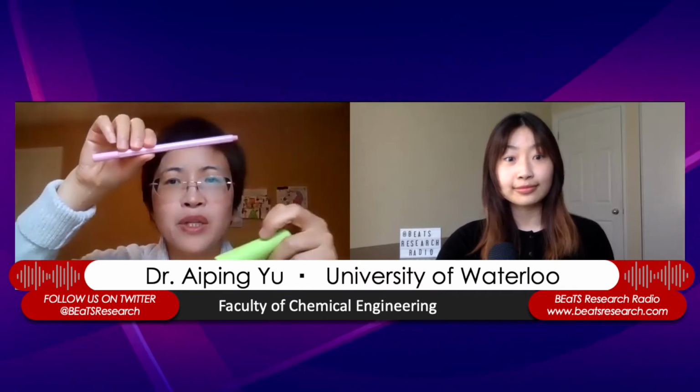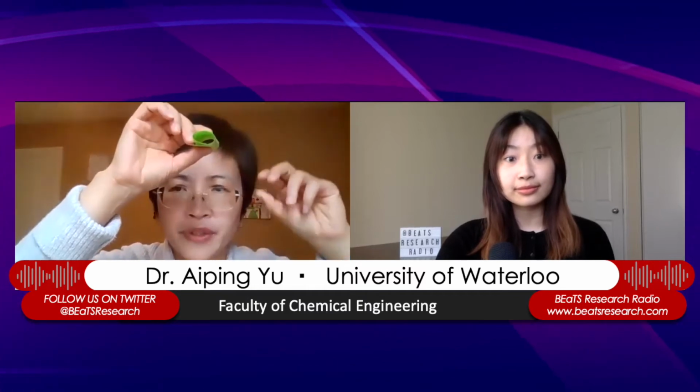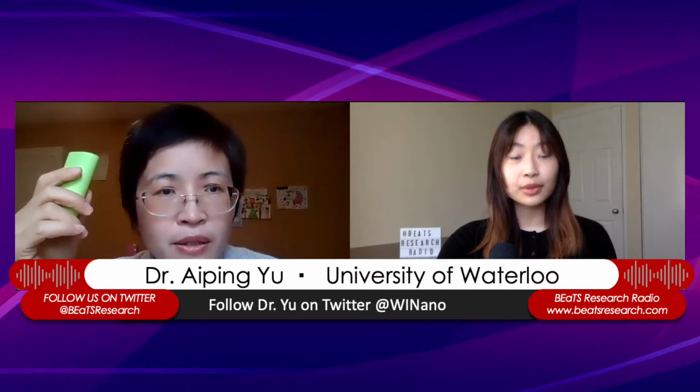Yeah, that's a very good question. As you mentioned, it's related with property. The first property that is different and also amazing is electronic property. For example, single wall carbon nanotube, these materials could be metal. Basically one type, it means this tube, the diameter and the angle, how you roll this graphene sheet. If in some circumstance you get this type of single wall carbon nanotube, this nanotube actually is metallic. So it's like metal. It means electronic conductivity is as good as metal, even higher than some conventional metal like copper or aluminum in the wire.